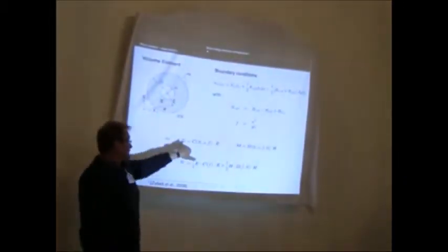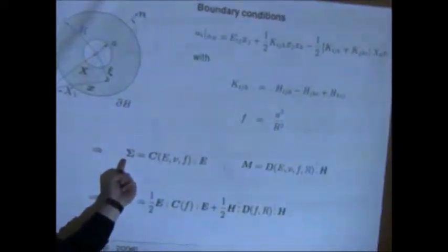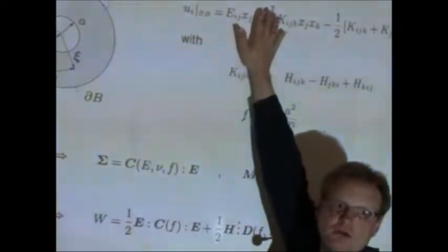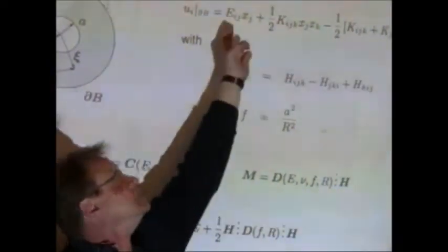Usually, in the usual representative volume element homogenization, you say you have a big volume element and the boundary data do not matter. And for random materials, you prescribe, let's say, constant surface tractions or linear displacements, and you solve the boundary value problem. You can define what average stresses mean: it's the integral of the stress field over your volume element. And you prescribe a displacement field which is directly related to average strains, and you can show that if you compute the integral of the strain field over your volume element, this coincides with the capital epsilon, the average strain, so to say. So average strain is related to average stress.